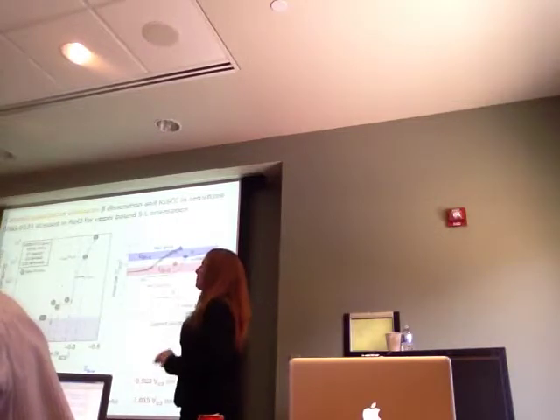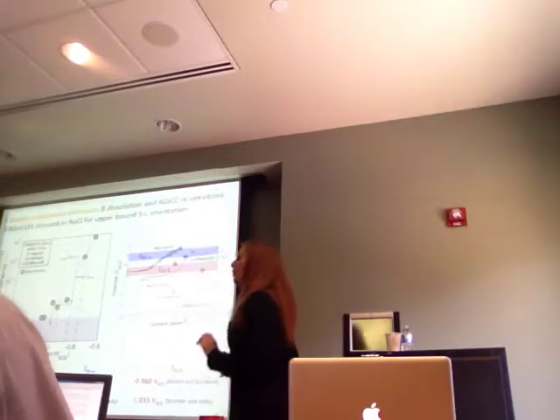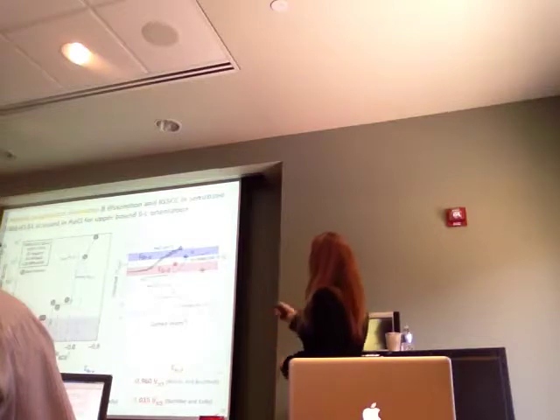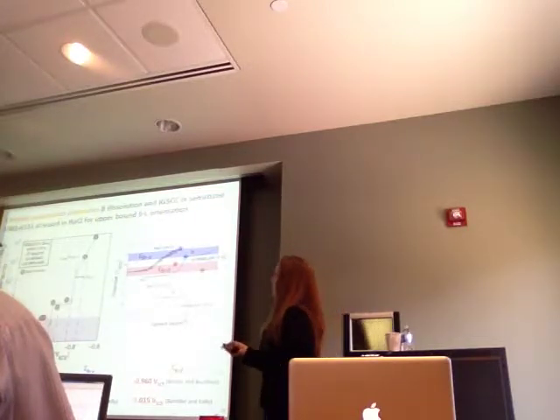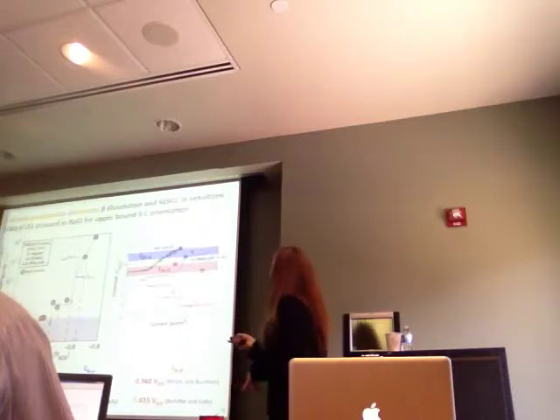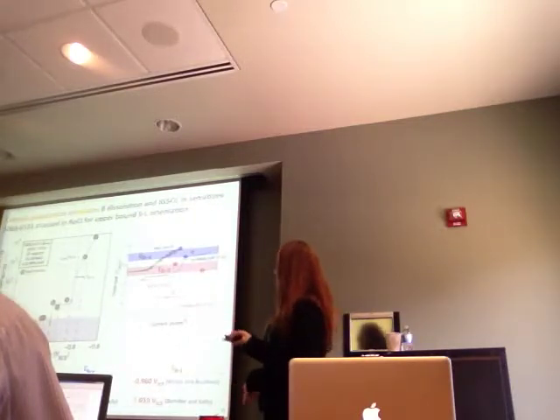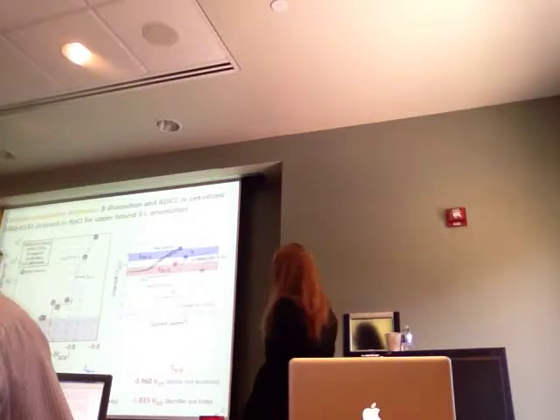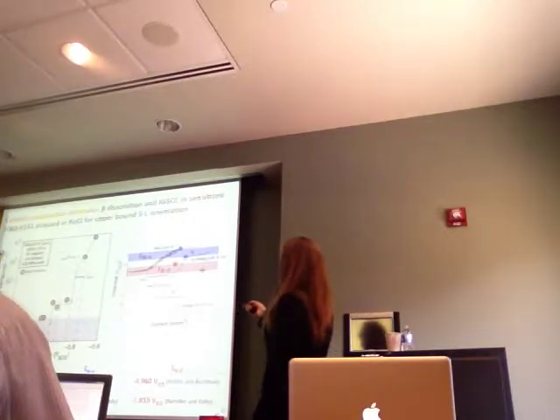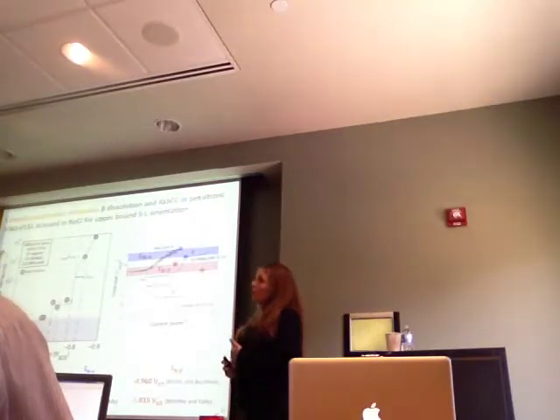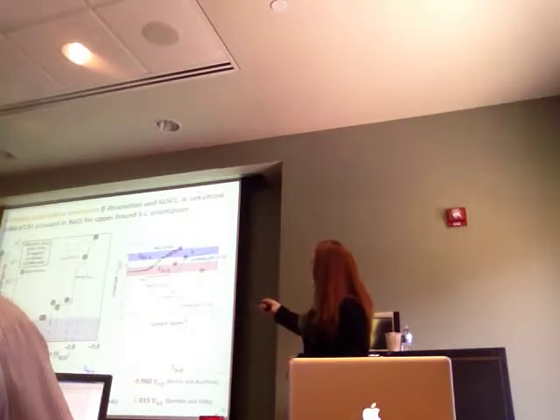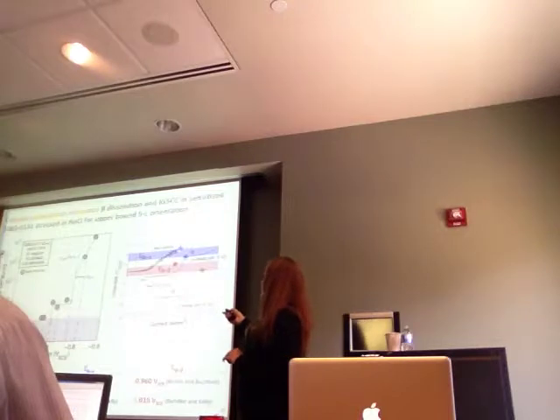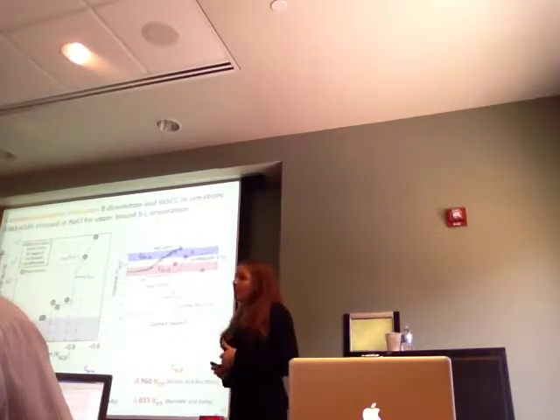Now what's really interesting is these ranges that I've plotted here. This range is the breakdown potential of alpha. And the way we get the breakdown potential of alpha is by looking at these black lines up here. I've plotted a polarization curve, which shows you the potential and the current. This top black line was in sodium chloride. So you can see that at a certain potential, your current takes off. When your current takes off, that means that you're rapidly dissolving alpha.